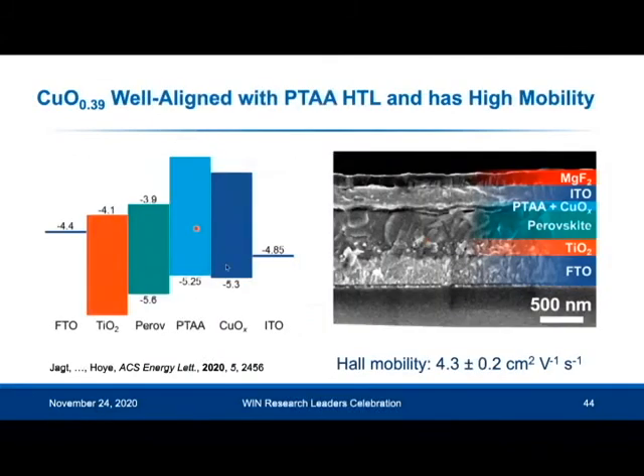So here you can see the device structure and the device stack. This is the cross-sectional SEM image of our semi-transparent devices, where we have FTO as our substrate. This is a transparent bottom electrode, and we sputter ITO as our transparent top electrode. We have PTAA as our hole transport layer, and between the PTAA and the ITO, we have our 3 nanometers of cuprous oxide. And one of the questions, of course, is if it's only 3 nanometers thick, is that enough to protect the perovskite from sputter damage? And the answer is yes, it is.